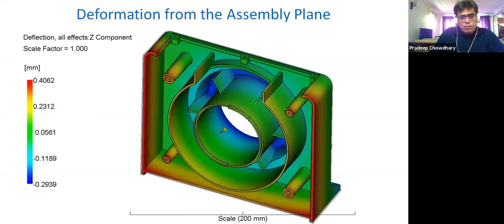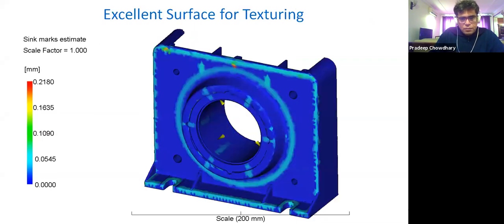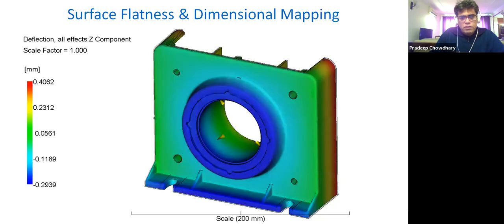So as you can see, the distribution is extremely even with the balanced gating, and this became a non-issue with the change of material. Also, the sink marks, if you look at the cyan region, they dropped from about 100, 120 microns to just about 50 microns. So that was a major improvement as well.